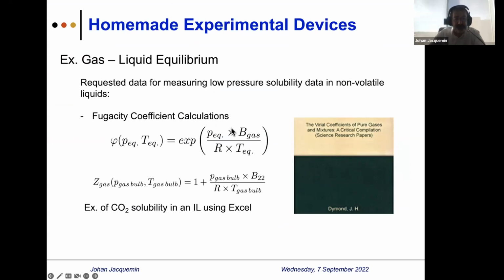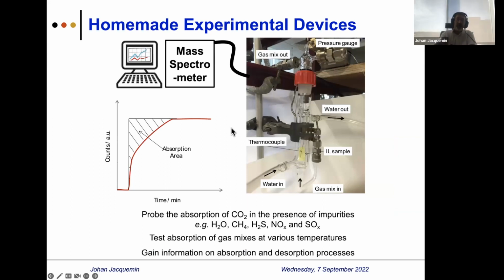And we also develop techniques using mass spectrometry, because if we want to measure the gas phase, we must do so, and honestly, it's one of the techniques which may be the most accurate, and simply that you can adapt and couple with different techniques. And this has been used to measure the absorption of CO2 in the presence of different impurities in ionic liquids that we published